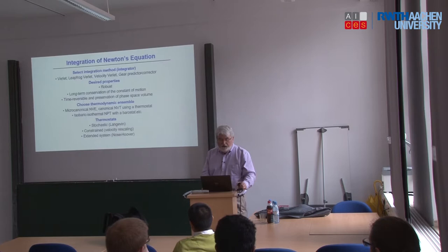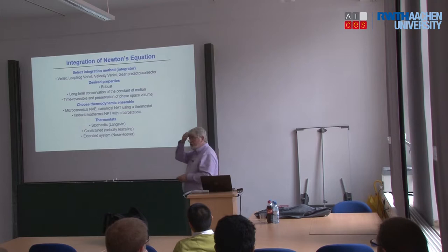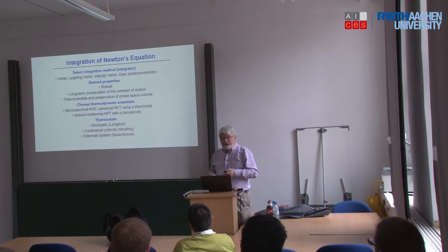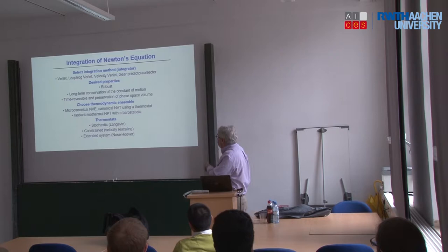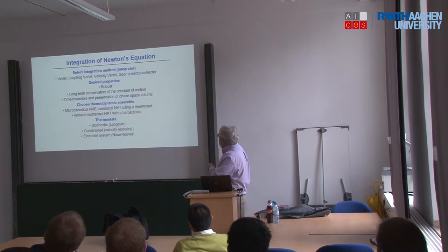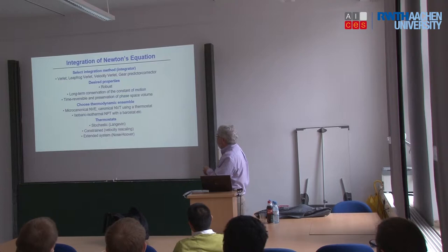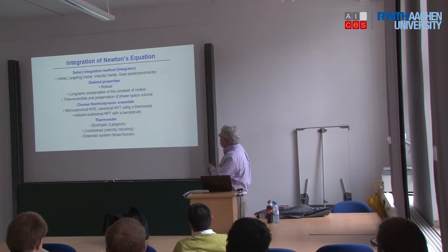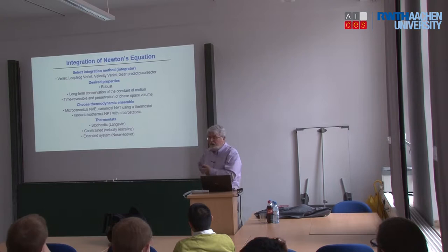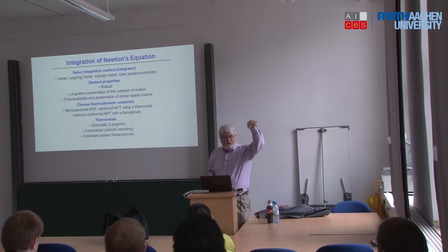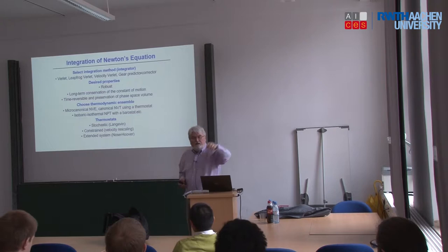So we have to integrate Newton's equations of motion, and there are various ways to do that. And I'm going to explain one method, which is simple and robust. So you have to select an integrator, and here's a number of ones which you would run across in your studies. The Verlet method, which is the one we're going to talk about, it's very easy to illustrate, and then leapfrog, different variations of Verlet. And there's something called a predictor-corrector method, of which the Gear method is quite a common one. So these are ways of advancing the equations. You can calculate from the positions at one time and the forces, the position at the next time. And you're going to do that as a function of time.